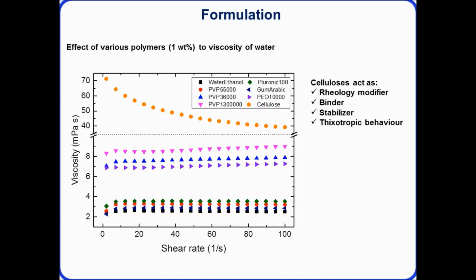So we can use cellulose as a multifunctional material. It can improve the rheology. It can be a binder for the material. It can also improve the adhesion on certain substrates, and it can help stabilize the graphene flakes in the solution.